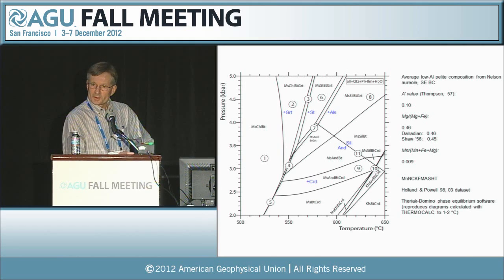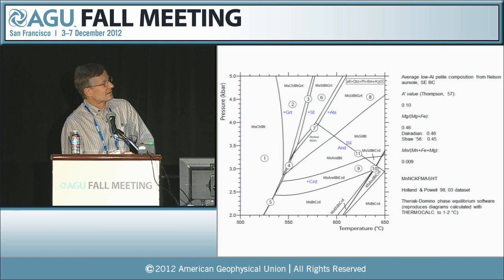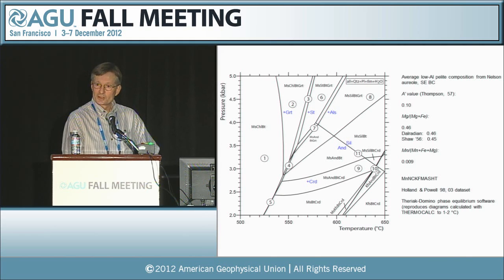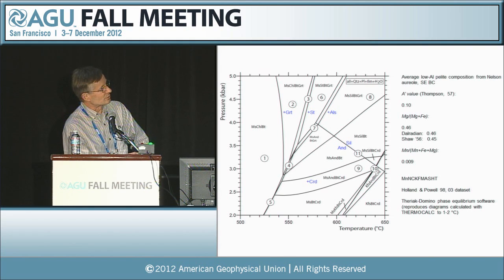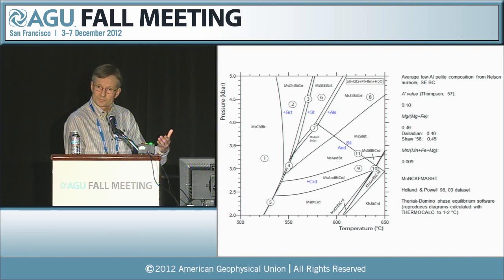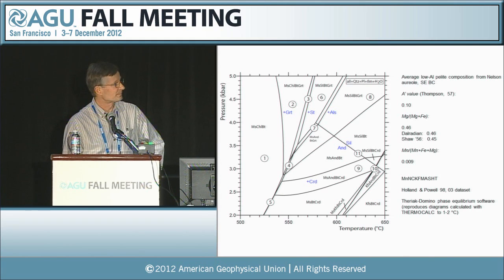If you look at an ordinary phase diagram, there's no indication of these differences at all. So this is an example of a P-T phase diagram, 2 to 5 kilobars, 500 to 650 degrees C. This is a map of the minimum free energy configuration of the system, but there's no indication as to the relative energetic differences between, say, adjacent domains on either side of one of these mineral-in or mineral-out lines, or indeed of competing configurations. So there's nothing that would give you something to predict as to where overstepping might be important or not.